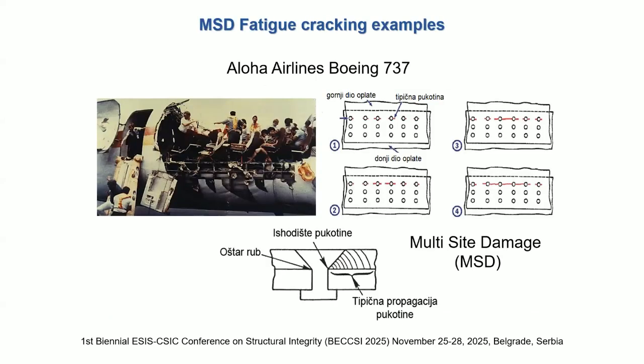So what is multi-site damage? Fatigue cracking examples. Here we see an Aloha Airlines Boeing 737. This accident occurred in 88 or 89, I don't remember. So what we have here, we have at the upper rivet row initiated cracks at the rivet locations. And then on the surface, loading under cycles which are caused by landing and taking off. Cracks are initiated, they propagate, they collide, and in this case, large-scale damage is generated.